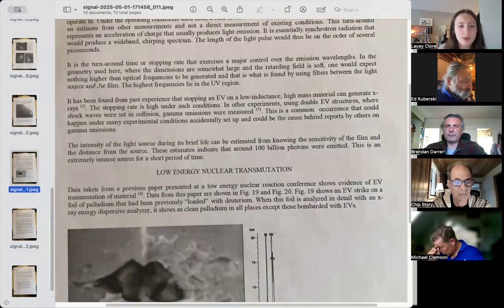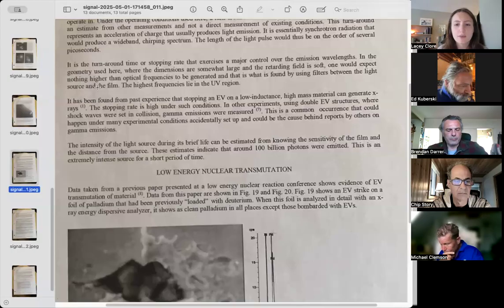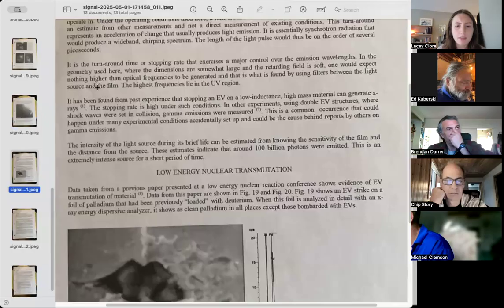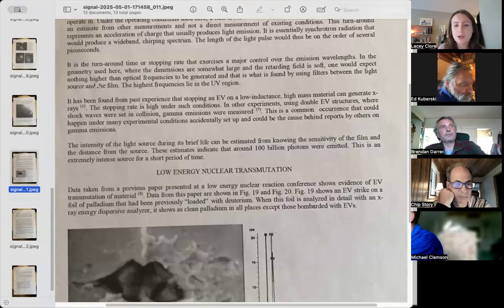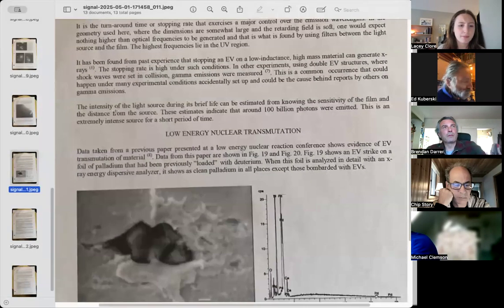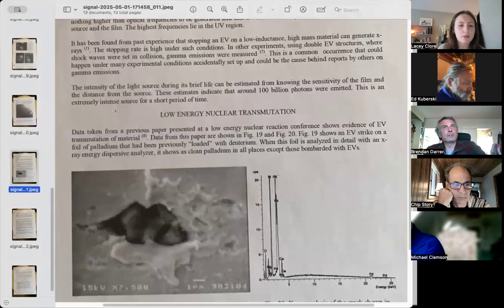In the geometry used here, where the dimensions are somewhat large and the retarding field is soft, one would expect nothing higher than optical frequencies to be generated, and that is what is found by using filters between the light source and the film. The highest frequency lies in the UV region. It has been found from past experience that stopping an EV on a low inductance, high mass material can generate X-rays. The stopping rate is high under such conditions.